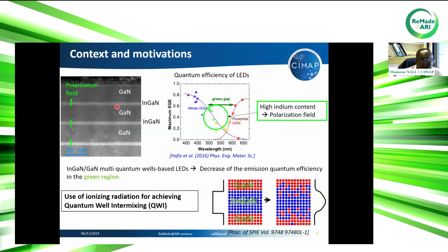And by doing this, we create a polarization field across the quantum well, as illustrated here. This polarization field will separate charge carriers, so this will decrease the recombination, and also decrease the light emission. So we decrease the efficiency of the LEDs. One way of minimizing this effect is by doing what we call quantum well intermixing. Typically, we go from a very sharp interface, like here, where we have a very nice interface between gallium nitride and indium gallium nitride, to a blurry one here. By doing this, we can decrease the polarization field. So in this study, we propose to use ionizing radiation in order to blur the interfaces.